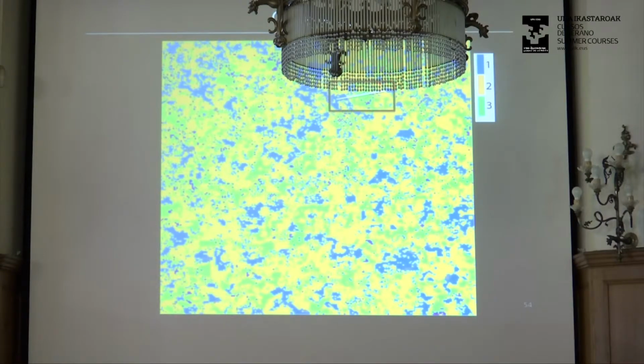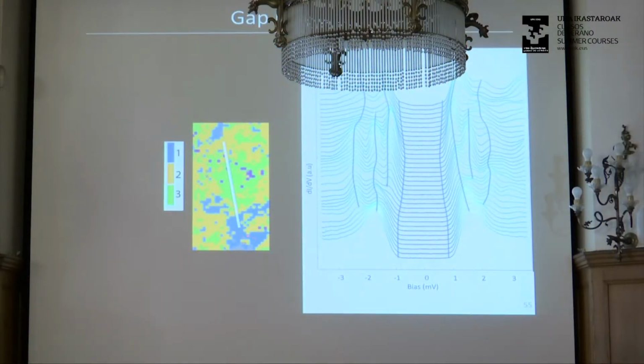So let's just focus on this area for a second, and I'm going to show you a line cut across here just to see what it looks like. Here, the blue region has what we would call 1 gap, which is what is picked up by a computer program, right? And the green region has 3 gaps. You start here with maybe 1, or we don't really pick up the shoulder. You immediately go into this region with 3 gaps: 1 coherence peak, 2 coherence peaks, 3, this is the 3rd coherence peak. And then eventually you end up in a region with 2 gaps here.